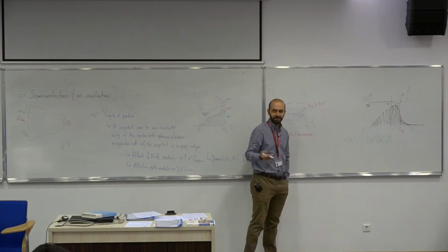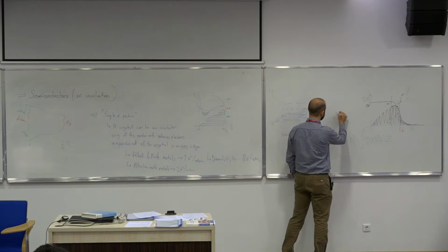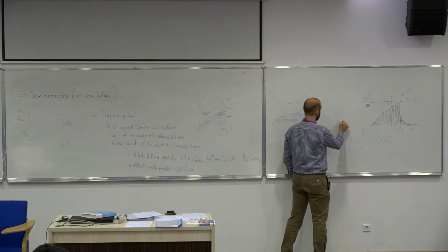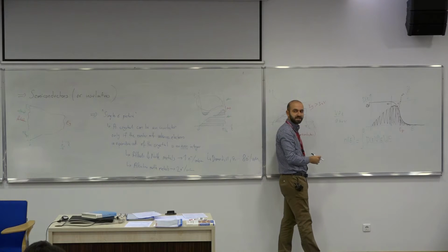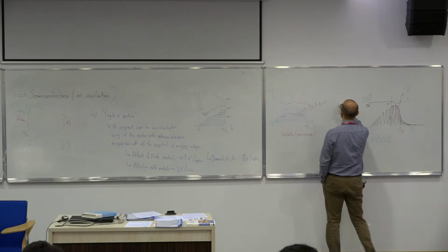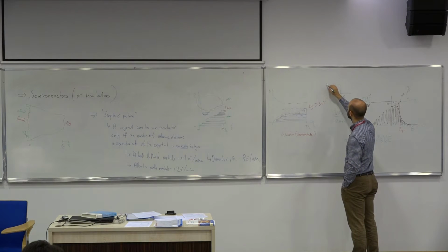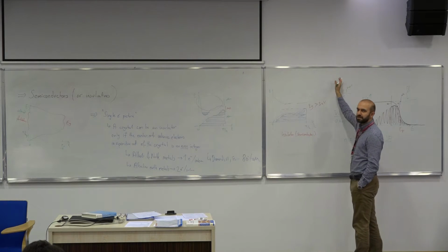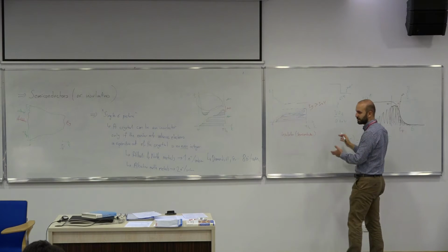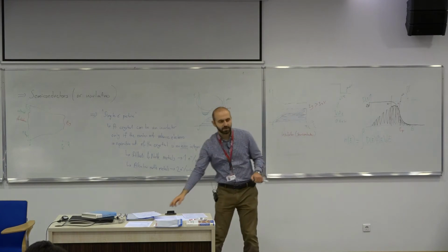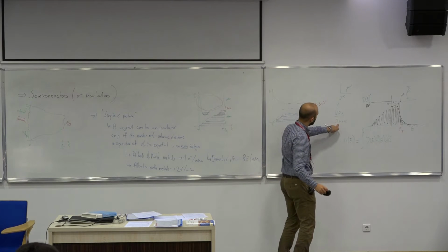For instance, there's this material, vanadium dioxide, one of my favorite materials. The energy gap is 0.6 electron volts, and at 65 degrees Celsius, the material is a semiconductor indeed, but it makes a very sudden phase transition. It becomes metal, and we call this a metal-insulator transition rather than a metal-semiconductor transition because an energy gap opens.